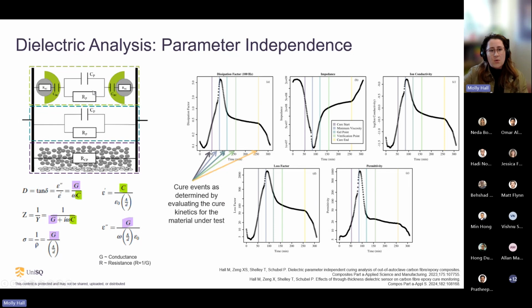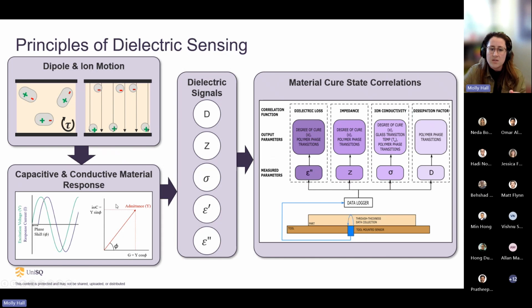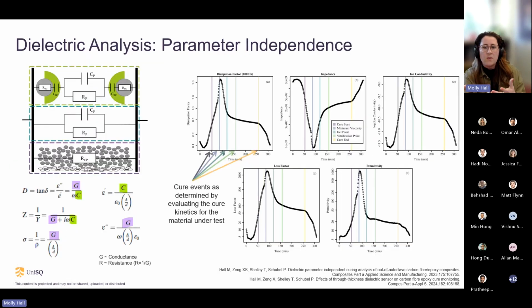So up here you see our equivalent circuit diagram. This is specifically for the through thickness sensor that I used, and it captures where the response comes from, depending on where your fibers are, where your resin is, and that interface between your fiber and your resin, and how that all contributes to the signal. So I have a bunch of equations up here, and these are your 5 dielectric parameters that we use. And what I want to highlight is all of these are driven by either your conductance or your capacitance. And because all of these are tied to those 2 parameters, which are tied to your material admittance, the first question is, why can't we use all of these independently, or why can't we use all of these interchangeably?